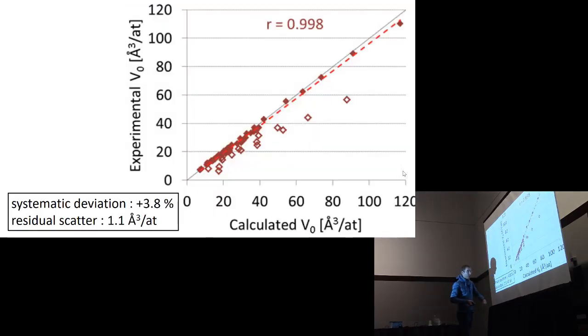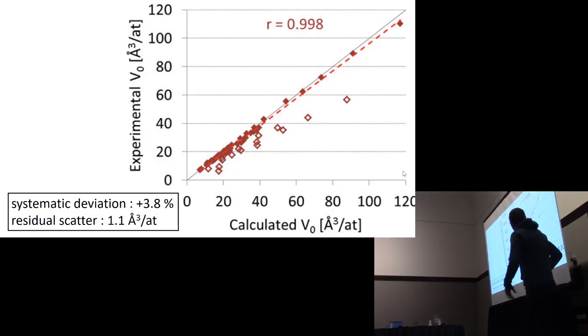That is the set we will study. For these 71 crystals, we calculate the equilibrium volume with DFT and compare that to the experimental equilibrium volume. These plots here are in cubic angstrom per atom. You see that a few points here do not follow the linear trend. Why do you expect a linear trend? If your PBE gives you exactly what would be measured in experiment, everything would be on this black line, the y equals x line. Most of them are, but these empty data points are not.